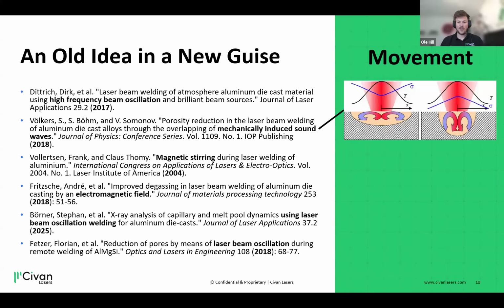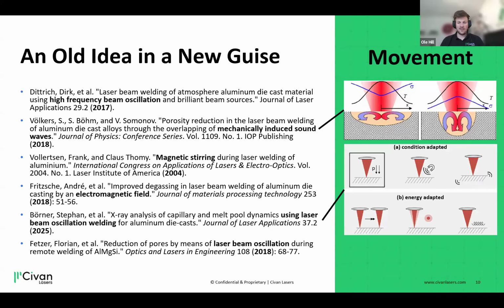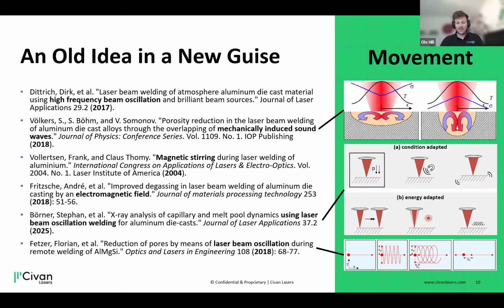You see something like mechanically induced sound waves. You even see magnetic stirring, some special moving optics, but note that they don't get as fast as our laser does. And some ultrasound magnetic waves, something like this, or moving the piece itself at very high frequencies. But all of these never got into mass production because they are too complex to adapt to a real workpiece. They might work in a laboratory, but overcoming the barrier to the market didn't succeed for these types of applications or these types of ways of inducing movement in the melt pool.